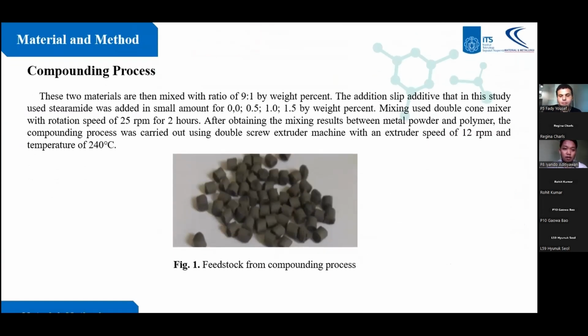To have a good composite material, there are several steps to fabricate the composite. The first step is the compounding process. These two materials are mixed with a ratio of 9:1 by weight ratio. Then the slip additive, which in this study is stearamide, was added in a small amount from 0 to 1.5 weight percent. The mixing used a double cone mixer with a rotation speed of 25 rpm for 2 hours.